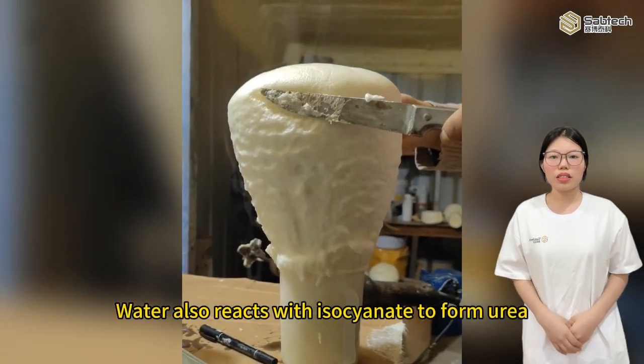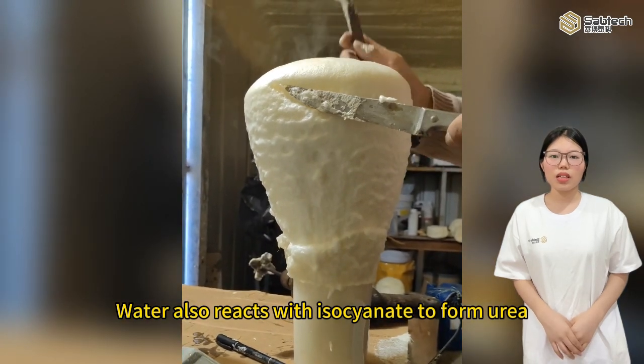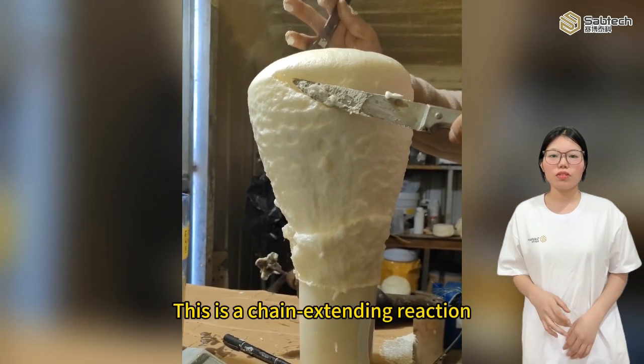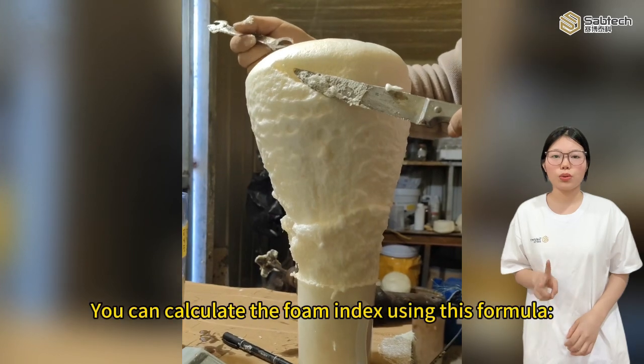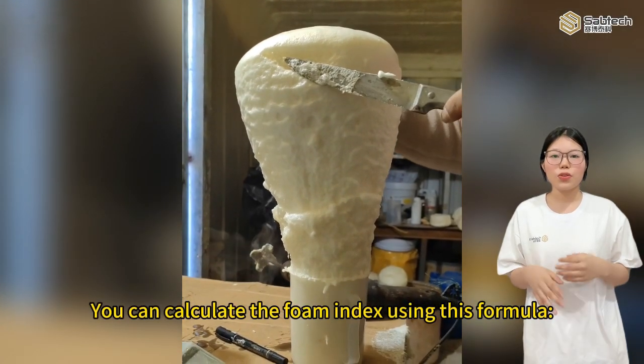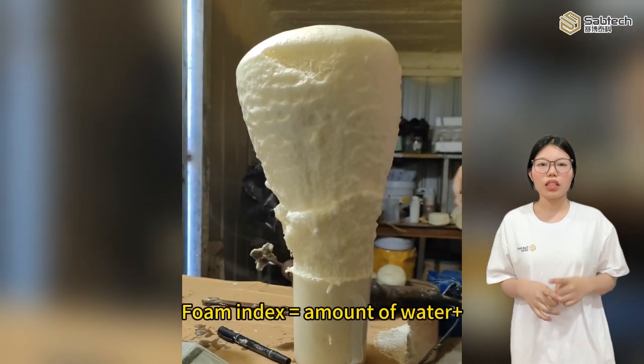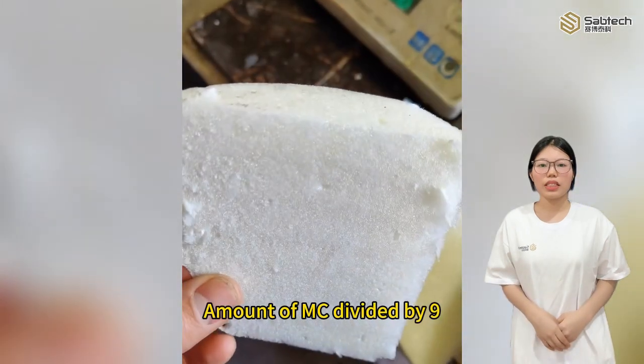Water also reacts with isocyanate to form urea and release CO2 and heat. This is a chain-extending reaction. You can calculate the foam index using this formula. Foam index equals amount of water plus amount of MC divided by 9.